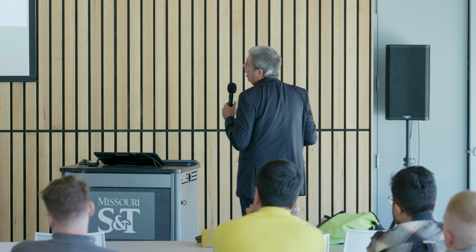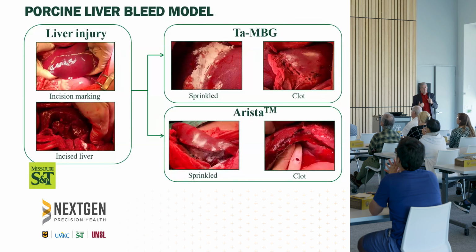What we don't know from that is how much tantalum is enough tantalum. We just see that it has a reduction, but is there an optimum amount of tantalum to cause that bleeding to occur? Now, tantalum is very expensive. Okay, it's really expensive. If you want to make 10 grams of this material, I think you were saying this morning it was about $200 to make 10 grams with a small amount of tantalum, with the lowest tantalum loading. If you go to a higher tantalum loading, that price goes up to $800 or $900. So it's important to know how much tantalum is enough.